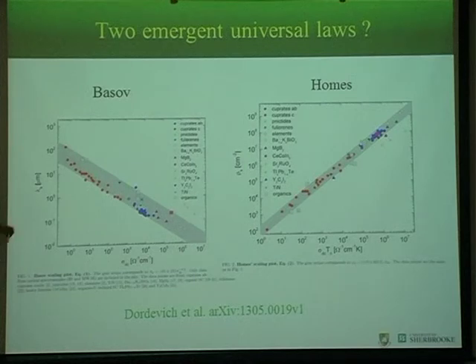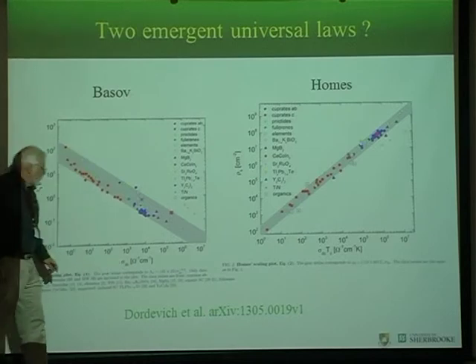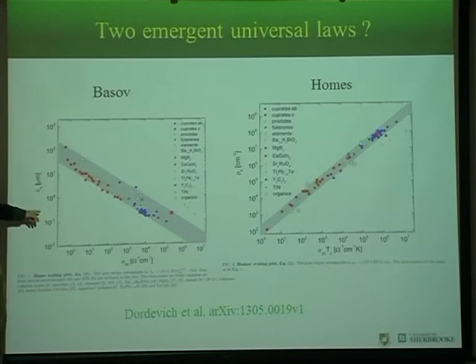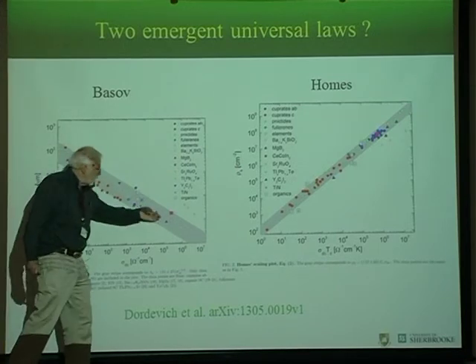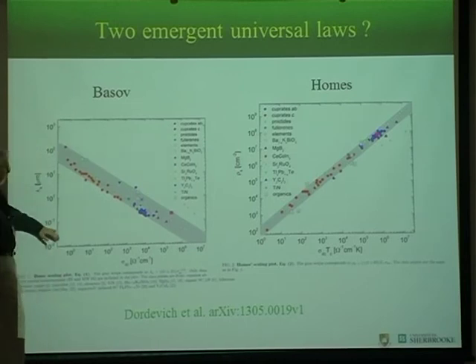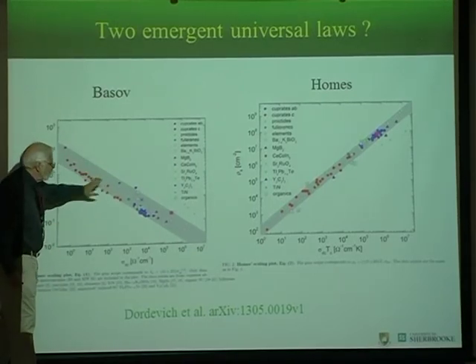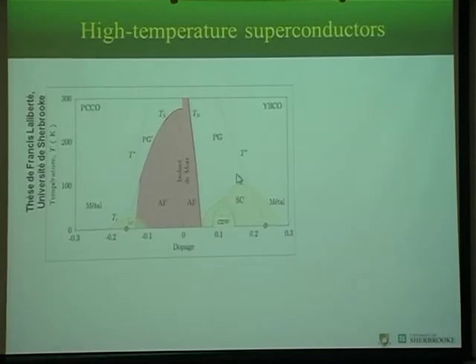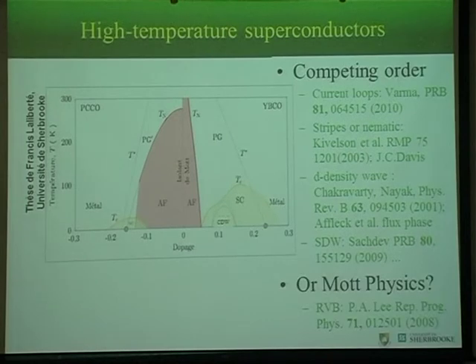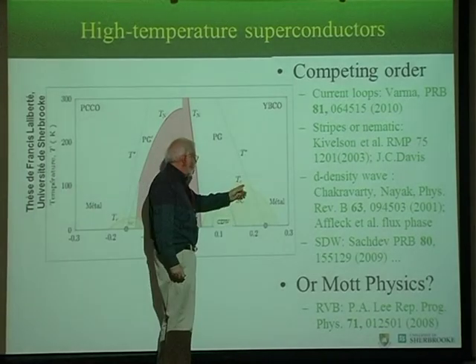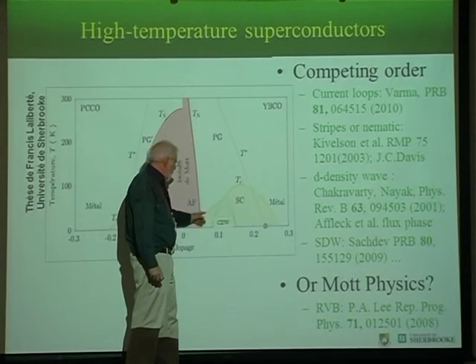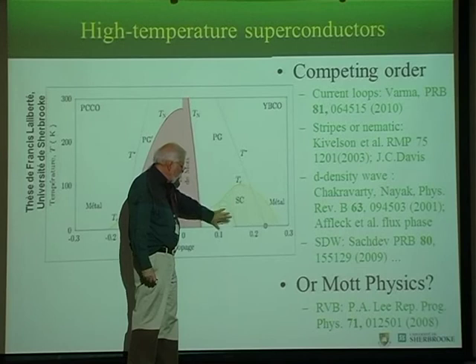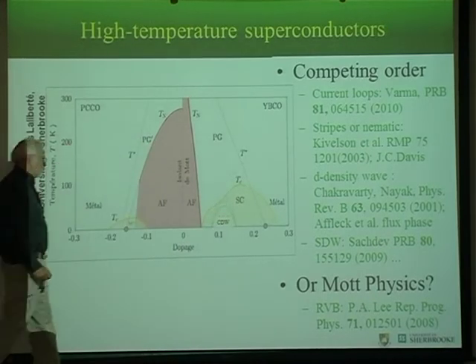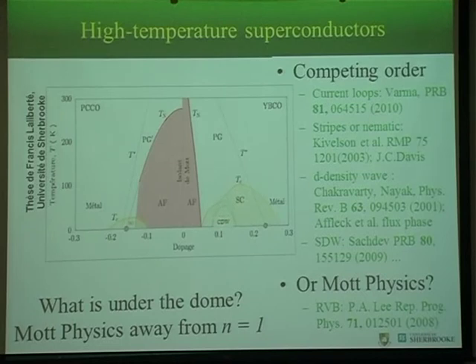At Tc. And here is the superfluid penetration depth as a function of sigma dc, along the c axis. And the power law now is to the minus 1/2. It is less convincing, but it's still many decades. Okay, back to this. So if we talk about the superconducting state, one of the questions is whether this is going down because of these orders, or if Mott physics is enough to do this. In other words, what is under the dome?